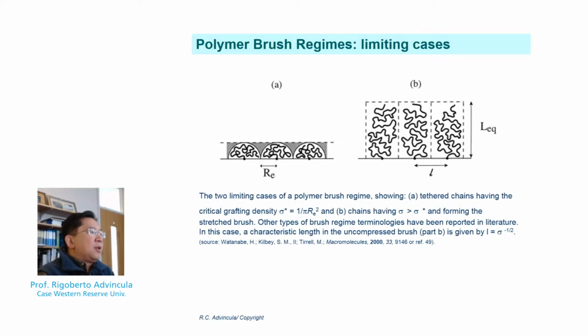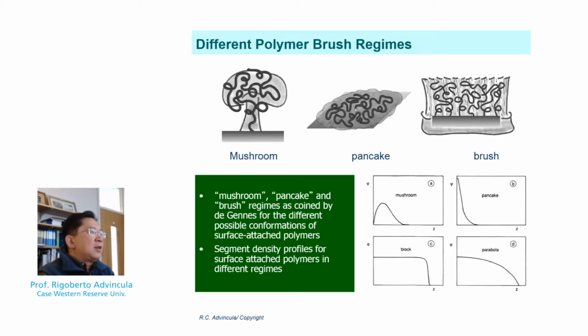So we are able to, for example, differentiate different regimes of a polymer. Limiting case, of course, is a very high grafting regime. Another is a very loose regime, and in between we have other types of cases. So the tethered chains can have a critical grafting density, and the chains having a grafting density can be forced to stretch depending on the temperature as well as the solvent regime conditions, or what we call compressed and uncompressed brush. Sometimes this can be best characterized by plotting the grafting density and the height of the brush, which can be observed, for example, with techniques like X-ray reflectometry or ellipsometry.